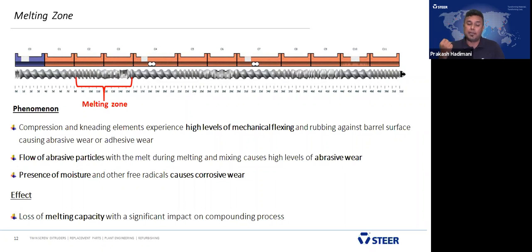What is the effect happening in the melting zone? The melting capacity drops because of the wear and tear and also because of corrosion and adhesive wear. That has a significant impact on the compounding process, because melting drops suddenly. That is the effect of wear.